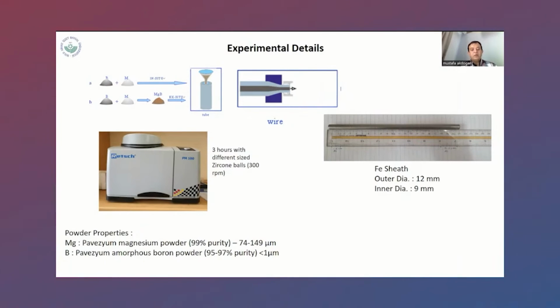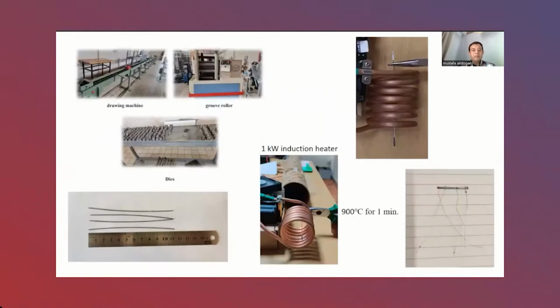We have applied to our mixture 3 hours of ball milling with a speed of 300 RPM. We have also applied drawing to our wires to reach the final diameter. At the beginning, our iron sheet outer diameter was 12 millimeter and inner diameter was 9 millimeter. You are seeing the drawing machine in our laboratory and groove rolling machine. These are the dies. Finally, we get 1 millimeter diameter wires, and we closed each end with the mechanical press, and we have applied induction heating on these wires.